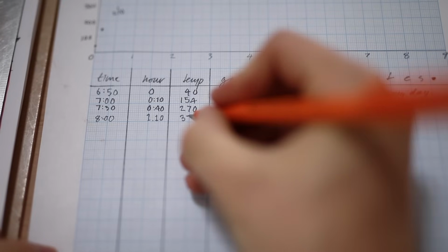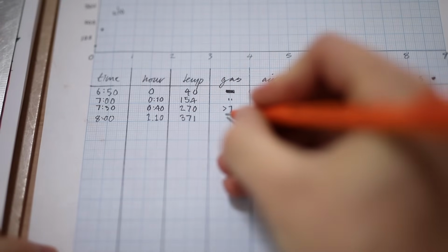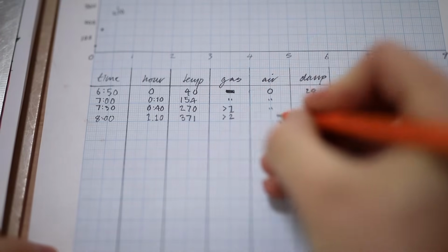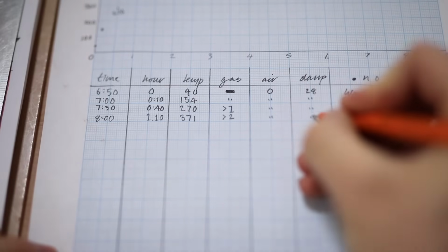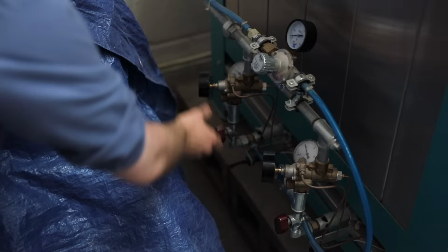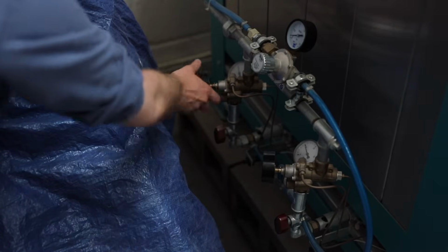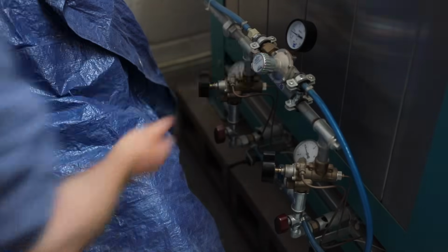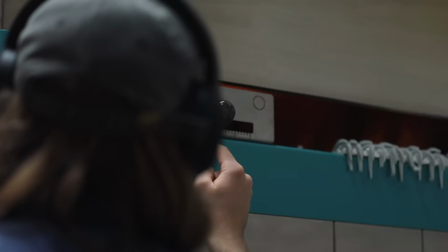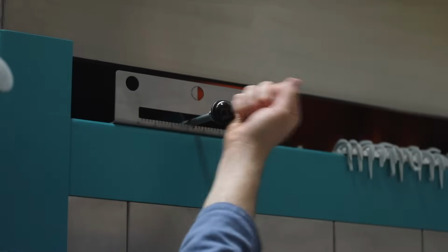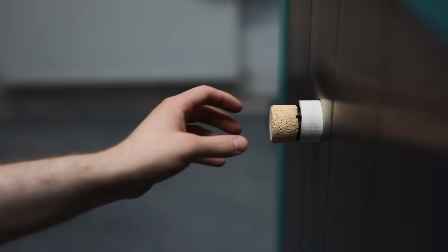The first bit of real excitement happens at 860 degrees Celsius. At this point I turn the gas pressure and the air pressure up significantly, and I close the flues that cover the back of the kiln about halfway. This causes too much gas to accumulate inside the chamber, and there simply isn't enough oxygen present for it to burn properly. As a result, the burning atmosphere ends up stripping away oxygen from the clay and glazes themselves, thus changing their colour and creating tones and textures that can be rather difficult to recreate with an electric kiln.